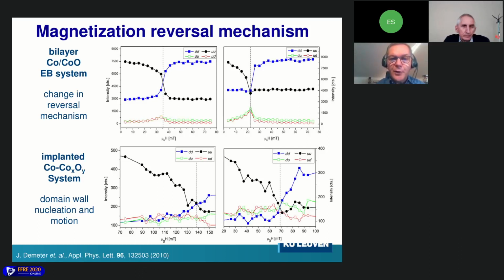And here I draw your attention mainly to these graphs at the bottom in red and green, because they are the so-called spin flip intensities. Remember, this is providing information about the component of magnetization perpendicular to the applied field. If you have a process of reversal by only domain wall nucleation and motion, there is hardly any component perpendicular to the field, like here. But when there is a process of rotation of the magnetization, you see a peak in this spin flip.